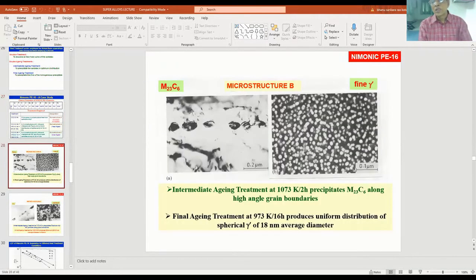Here you can see microstructure B, which is given double aging treatments. At the grain boundary, you see that the grain boundary is a matrix, and these are the discrete chromium carbide precipitates, M23C6 precipitates. This is the fine, spherical gamma prime, you can see that. That is the way it has been formed in the two treatments.